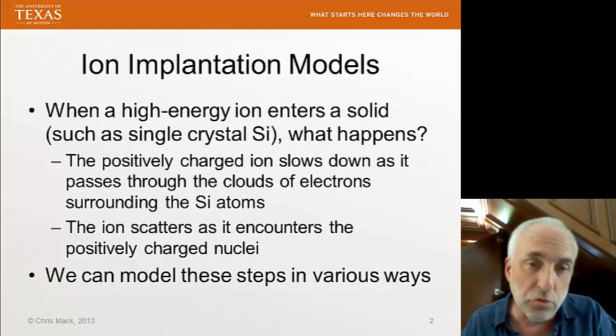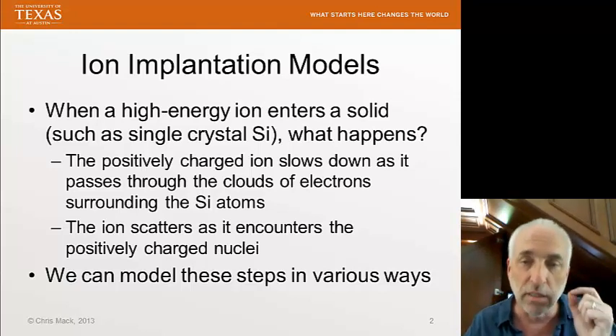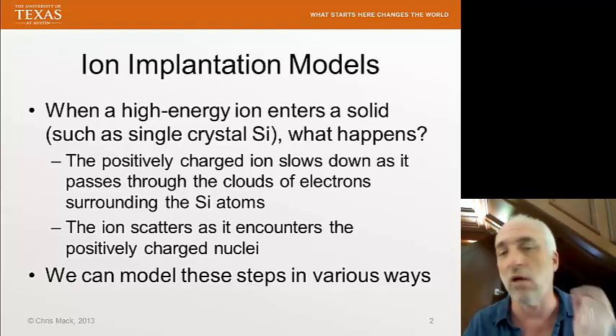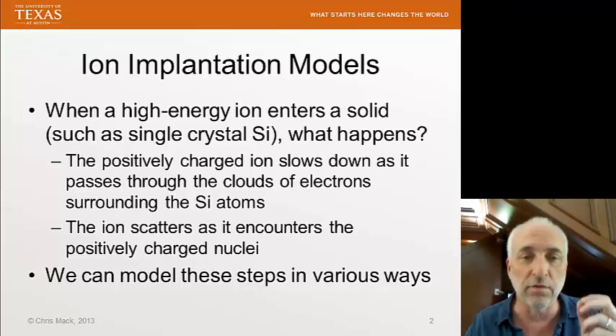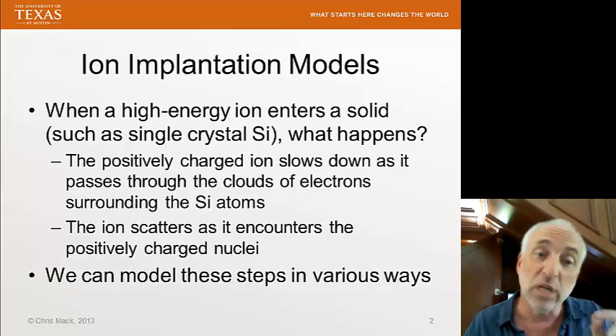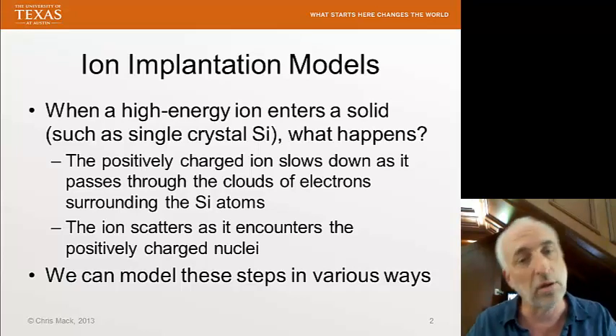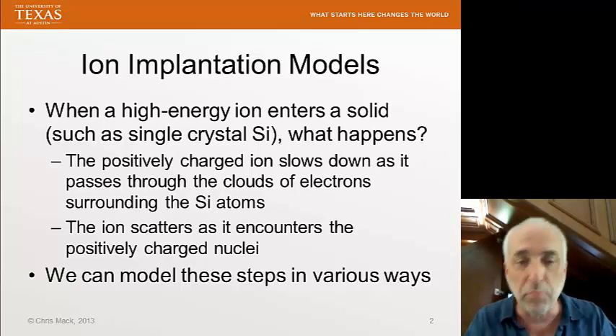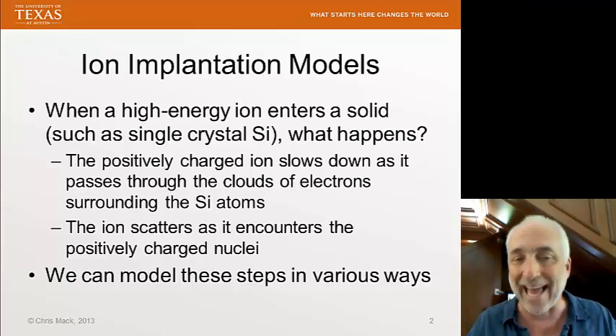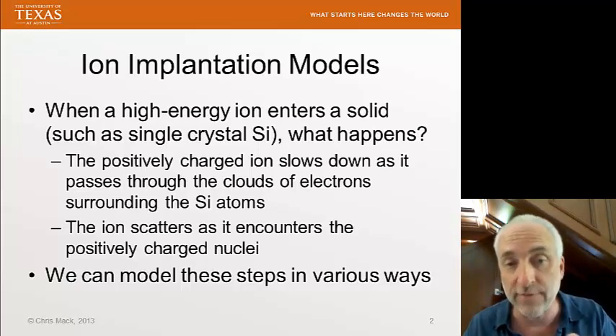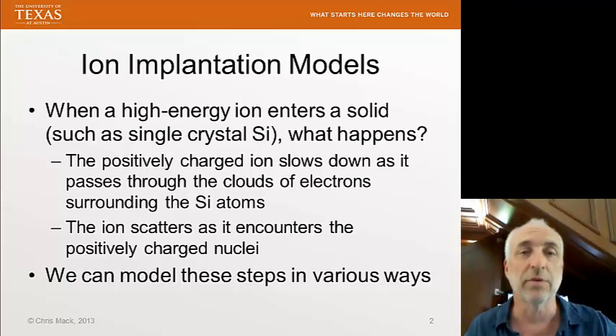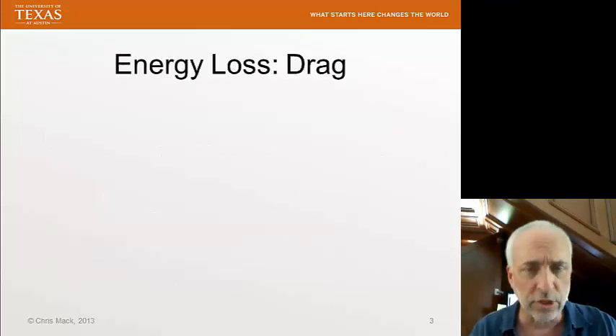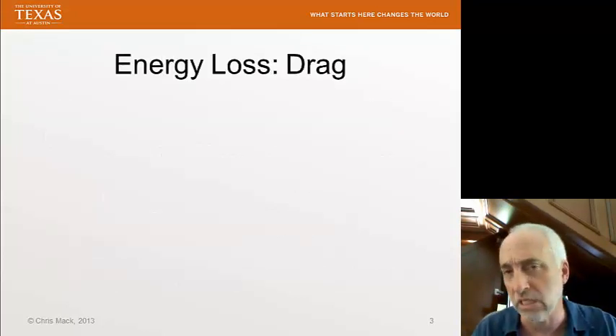As the positively charged ion goes through the cloud of electrons surrounding all the silicon atoms, there's a drag effect. It's going to slow down because of the attraction of the positive charge with the negative charges. But if that ion penetrates the cloud and gets close to the nucleus of the silicon atom, we have a positive-positive repulsion, and we get a scattering of the ion off of the silicon nucleus. We want to be able to model these steps, and we'll look first at that energy loss piece, sometimes called drag.